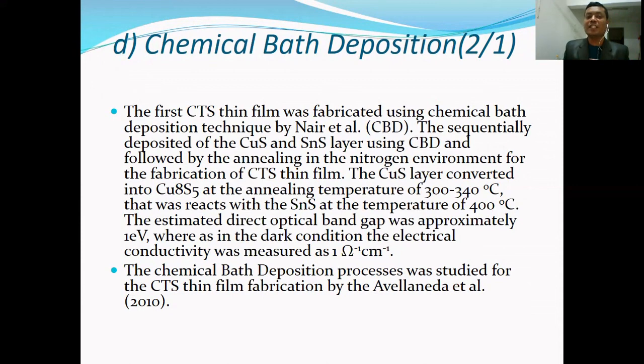The estimated direct optical band gap was approximately 1 electron volt, whereas in the dark condition, the electrical conductivity was measured as 1 ohm inverse centimeter inverse.